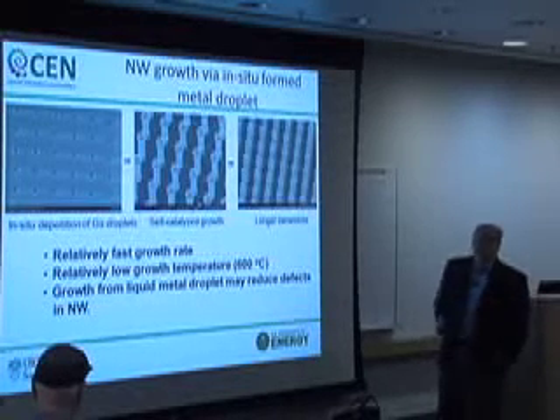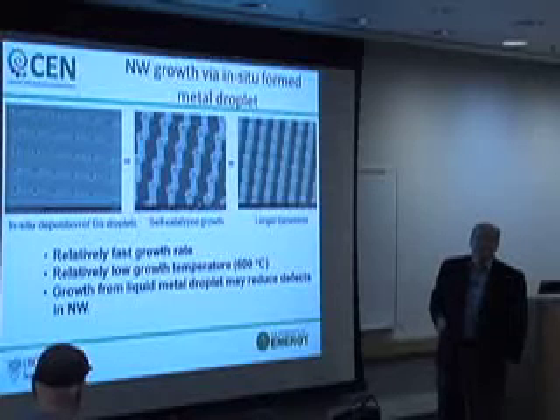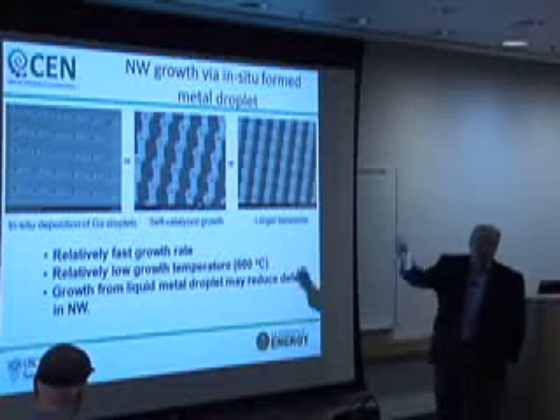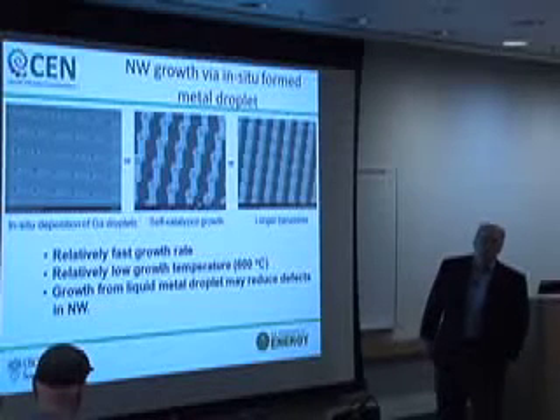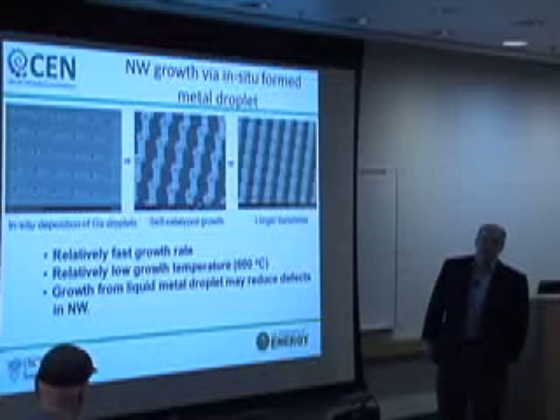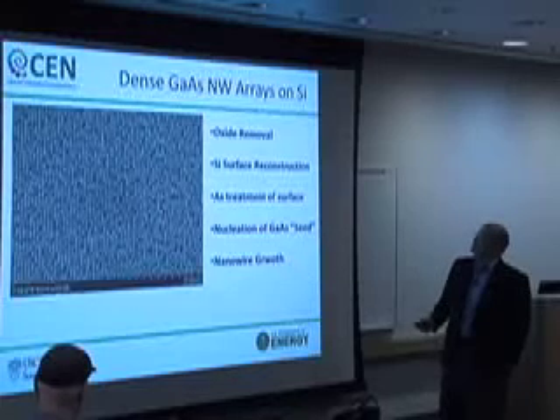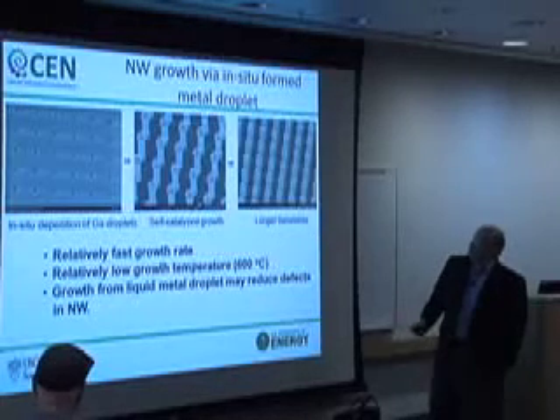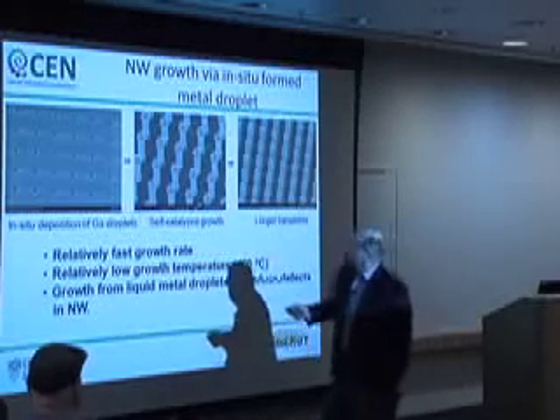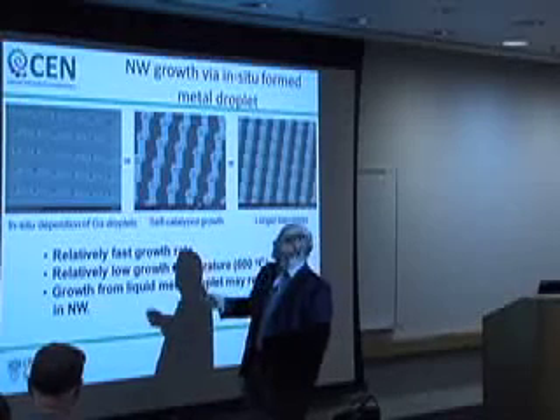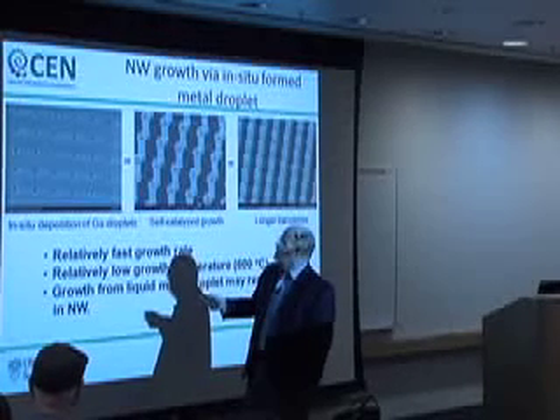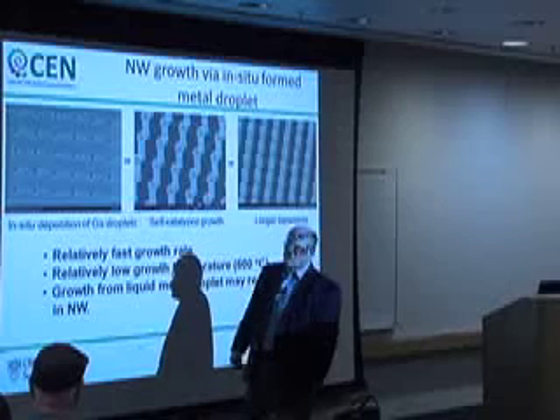So that's trimethyl gallium turned on? Yeah, and with no other, well, carrier gas, but no column 5 or anything else like that. And what's the spacing on that? In this particular case, it looks like they're about 500 nanometers apart and maybe a little bit more than 100 nanometers in diameter.